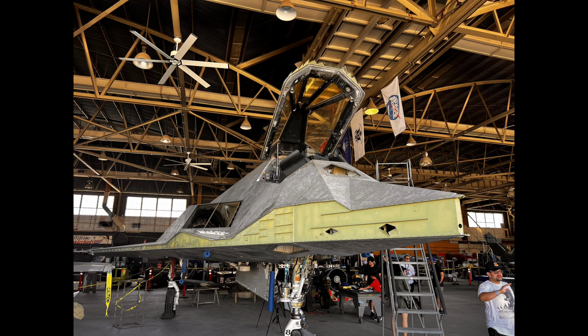Attention then shifted to the radar-absorbent material itself. Samples of RAM-coated panels were recovered in varying states of degradation. Laboratory testing focused on adhesion integrity, dielectric consistency, and thermal aging characteristics. Investigators found localized delamination zones where bonding strength had fallen below specification. These zones corresponded closely with areas exposed to maximum aerodynamic heating and vibration during routine flight. While this degradation had negligible impact on structural strength under normal loads, it altered the mechanical response of the skin during blast exposure. Without the damping effect of intact coatings, vibrational energy transmitted directly into the aluminum substrate, amplifying stress concentrations at fastener interfaces.